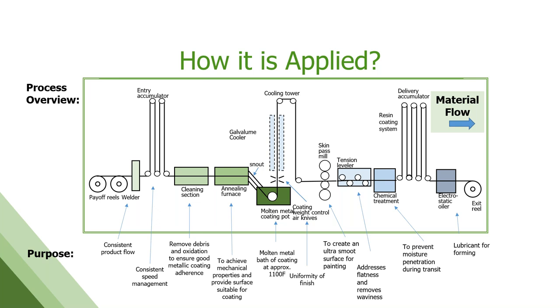So we're doing two things on this line, right? We're going to apply the metallic coating, but first we need to get the steel annealed to its correct mechanical properties and grade specifications for the end use. So that happens in the annealing furnace. Comes out of the furnace, heads into the molten pot, which I'll show in a little bit more detail in the next slide. So that's the molten bath of aluminum and zinc mixed in there in the right proportions. The strip goes through there, gets its coating put on. We control that coating with a set of air knives, high air pressure that thins it out to the right thickness and weight. Gets cooled down pretty much almost to room temperature, but significant cooling takes place.